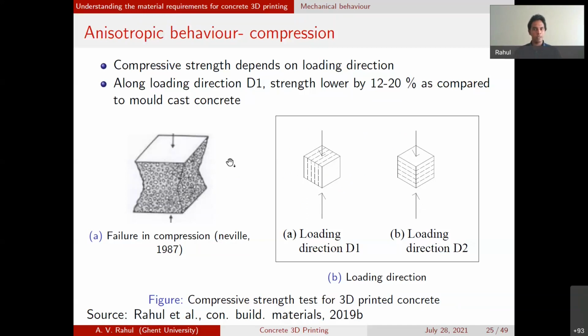Now, to understand this, you need to look at how failure of concrete happens in compression, which is depicted in this figure here. If you apply a compression load on the concrete, let's say in the vertical direction, then due to the Poisson effect, the concrete starts bulging laterally, and this bulging causes vertical cracks forming like this. Then the restraint from the loading frame at the top causes these cracks to diverge outwards like this.